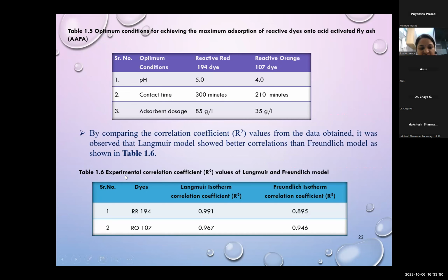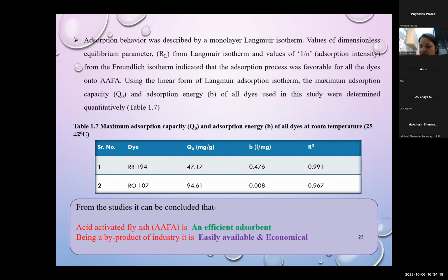Here is the result. We are calculating the experimental correlation coefficient R square value of the Langmuir and Freundlich isotherm models. For reactive red it is 0.99 for the Langmuir isotherm and 0.96 for reactive orange. In the case of Freundlich, it is 0.8 and 0.9. So from this data, we can say that the Langmuir isotherm model is more suitable and more favorable for the adsorption of dyes.